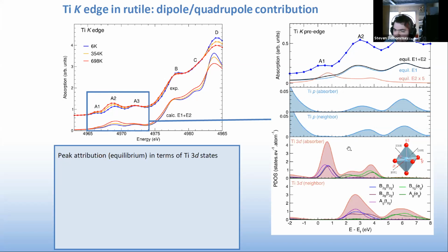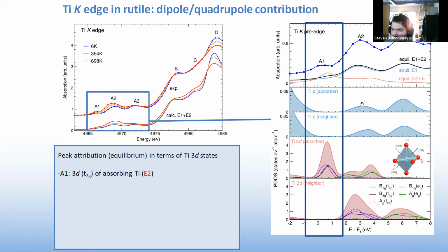And so using this projected density of states, we can kind of tell what 3D state is represented in each of these peaks. So we can assign each peak according to some transition to 3D state. So if we focus first on the A1 peak, we can see first that there is only a quadrupolar contribution to the spectra. The dipole is 0. And so we know that this peak is related to a direct transition to 3D state,